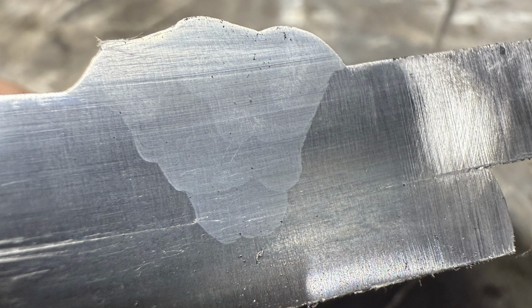And that's why with MIG welding tests, like on pipe, rather than doing an x-ray, they actually bend test it, because something like that might pass x-ray, but when you bend it, it fails, because what appears to be fused, even on an x-ray, might not be. So that super straight original bevel edge there is highly suspect. Everything else doesn't look too bad.